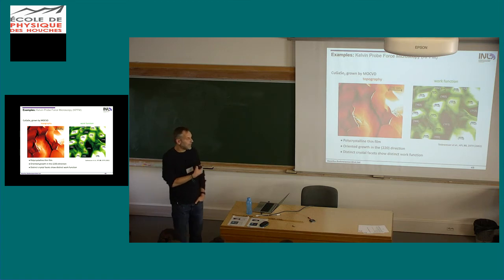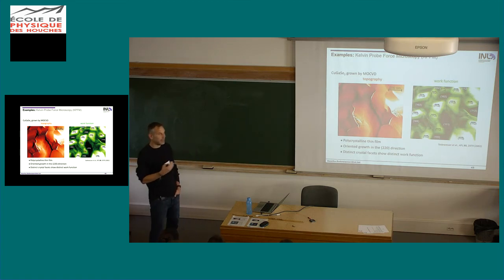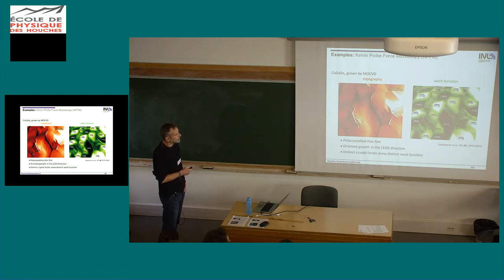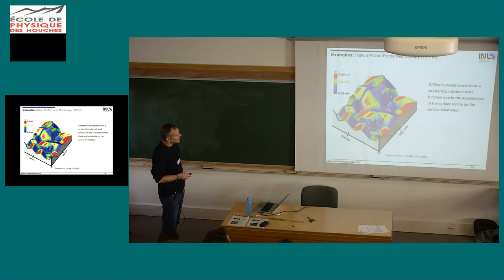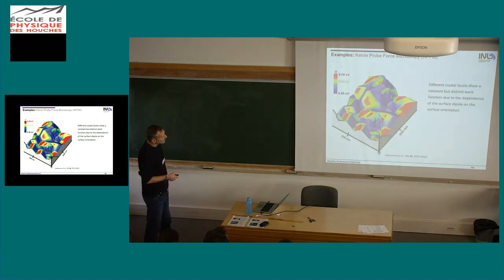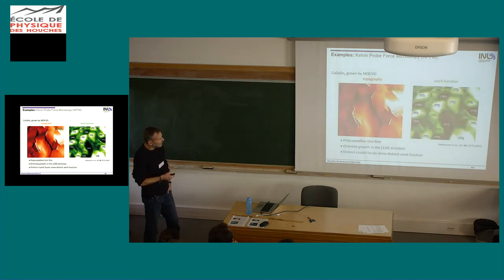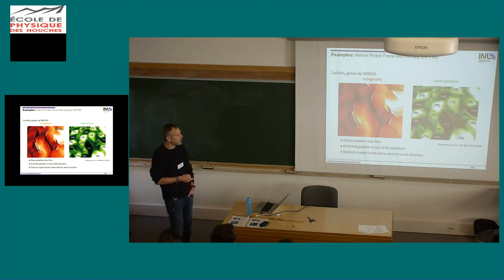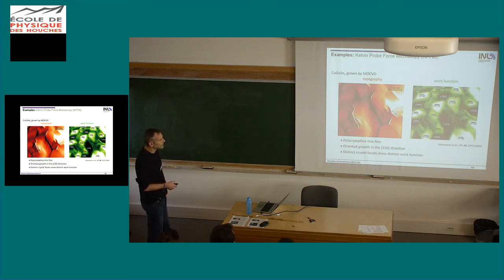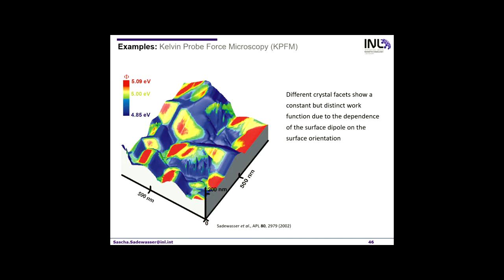Of course, this is an indirect measurement. It's not that we directly measure this, but this is the most probable determination of this facet orientation. And then, I think it's here, we can see that specific facets have specific work functions. So here we have a higher work function for these facets. There are these selenium terminated 112 facets, and lower work function for other facets.